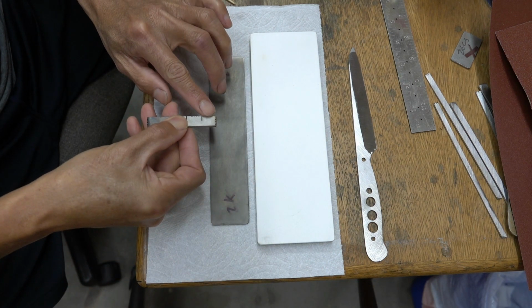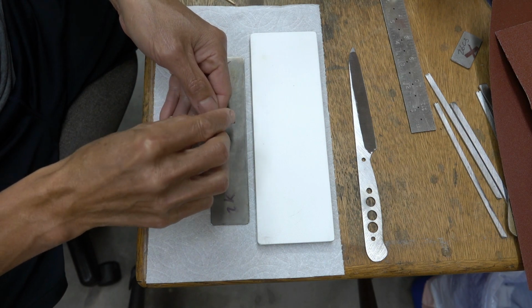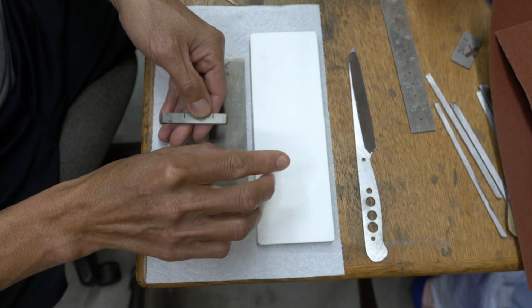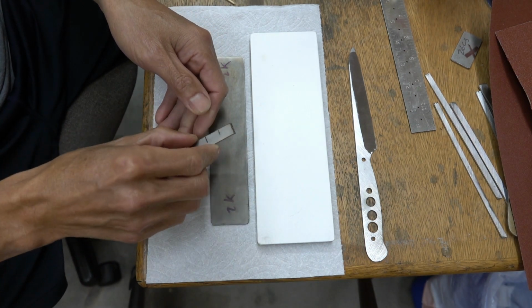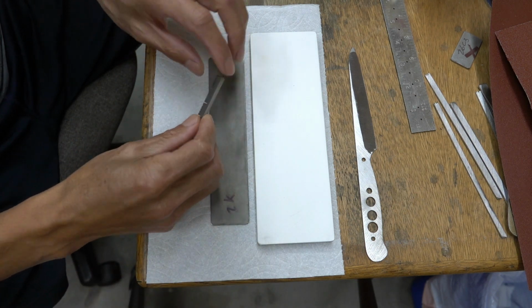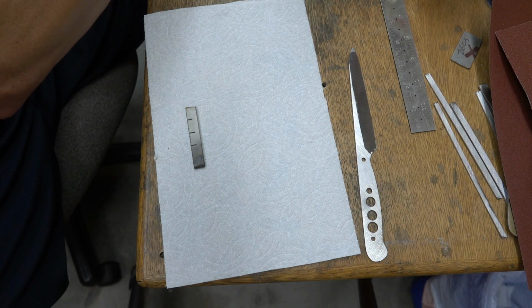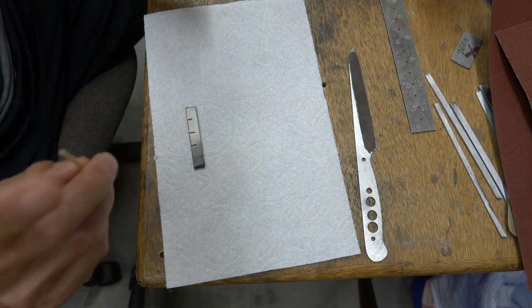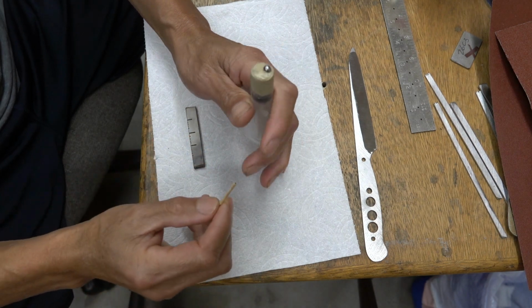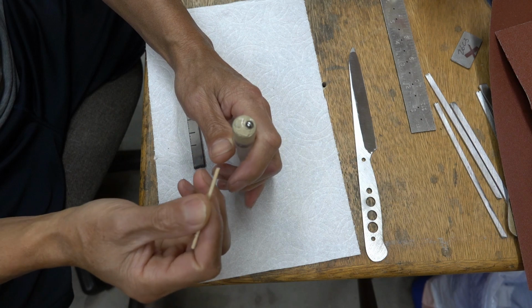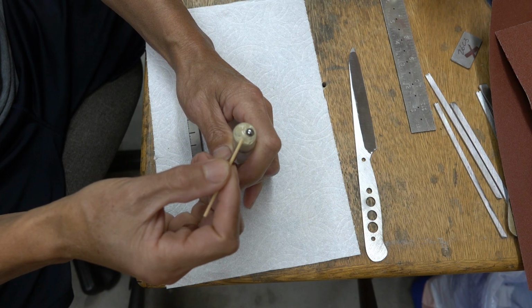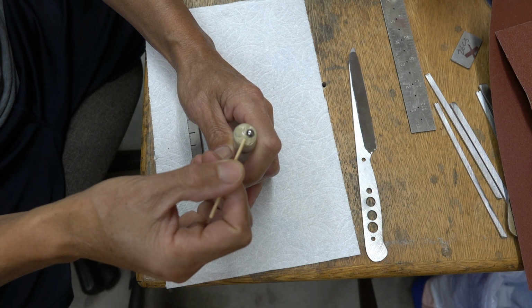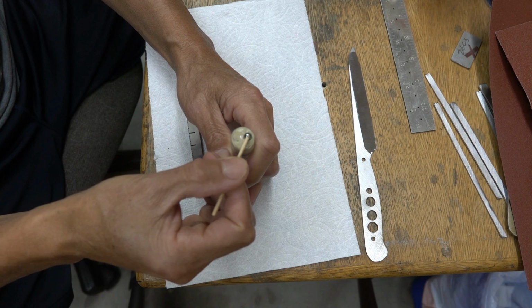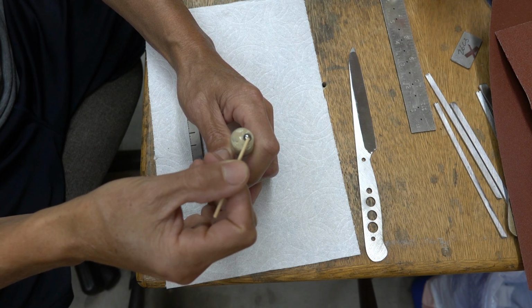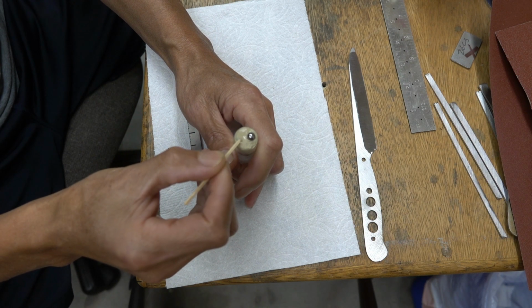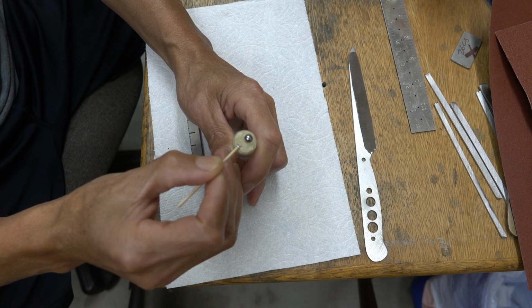We start out with a polished surface, but then what will it turn into after I use a softer abrasive? In this case, ceramic is very hard, but it's still softer than the carbide when you do the rubbing action. Now I'm going to make a visualization. I got silly putty here, and this silly putty simulates the matrix, and I got ball bearings that represent the carbide. So I got a matrix and carbide. Some carbide are below the surface right now.